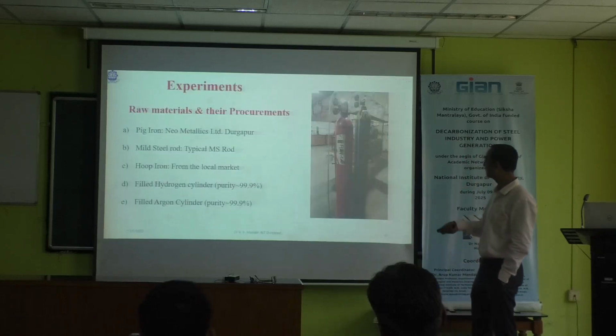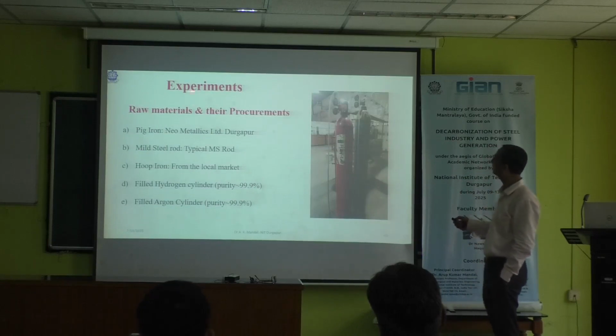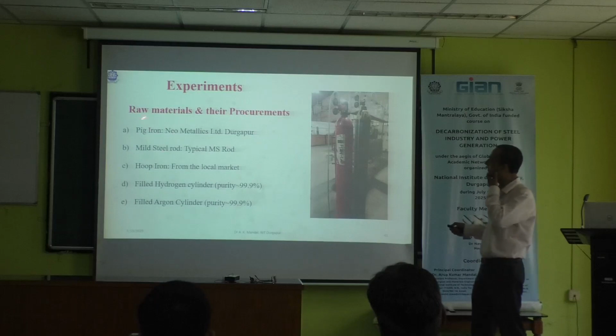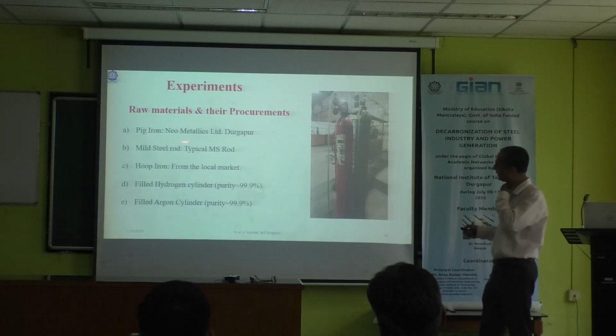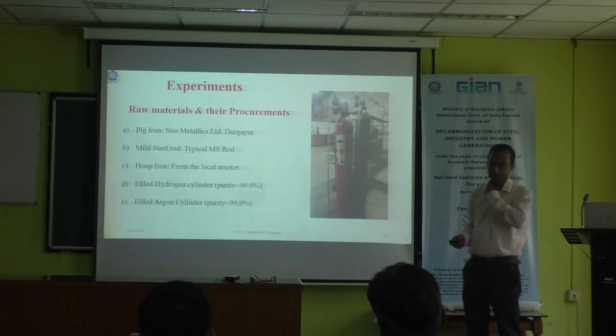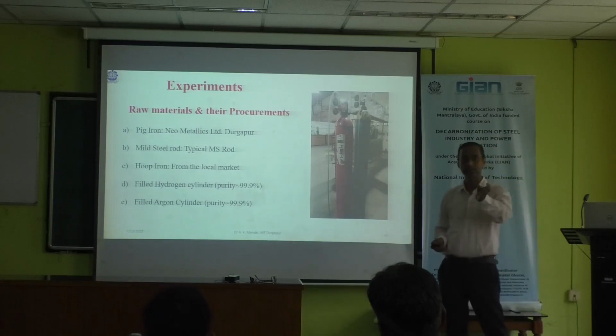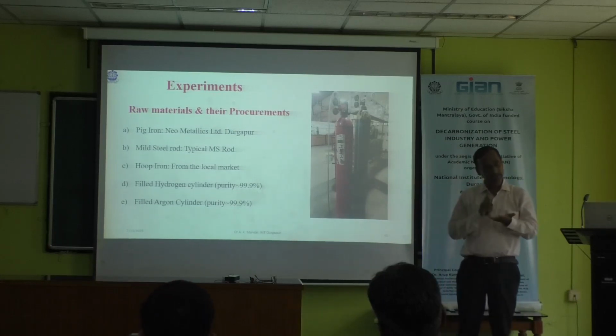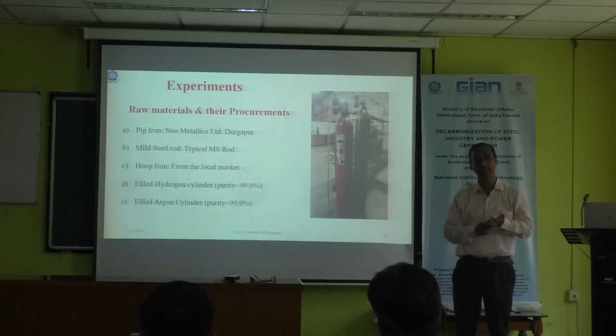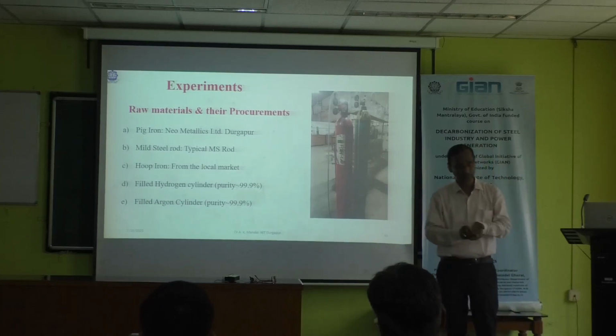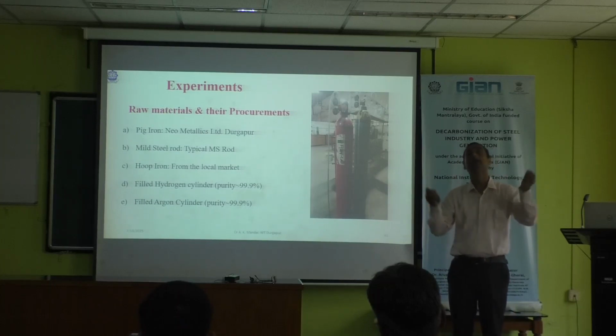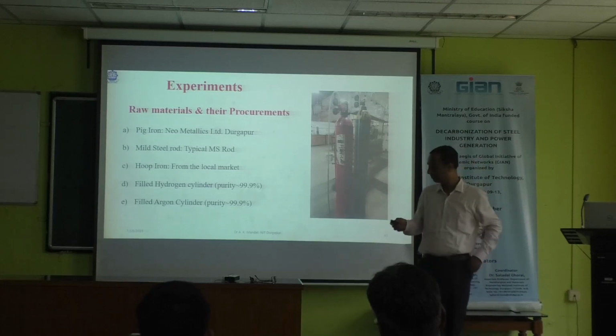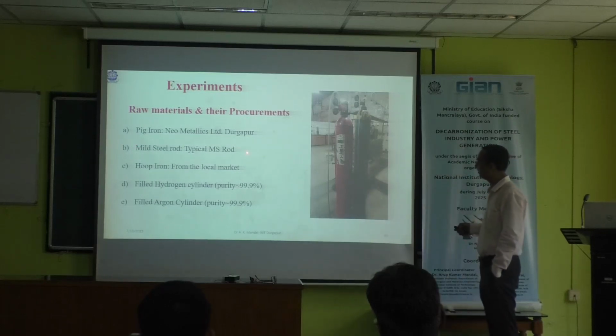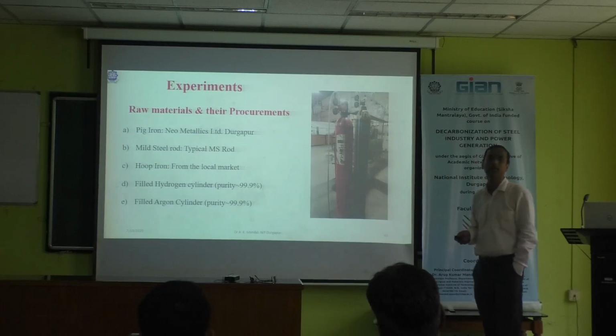Okay. Therefore, for the past experiment we have taken pig iron, typically high in impurities. Generally, when a blast furnace is under lining, if you collect a sample of the pig iron, it will have high sulfur and high silicon. There are some reasons: high sulfur is due to the lower part temperature, and high silicon is because of high coke consumption at that time. So typically you have collected some pig iron, and it is almost impurity free after treatment.